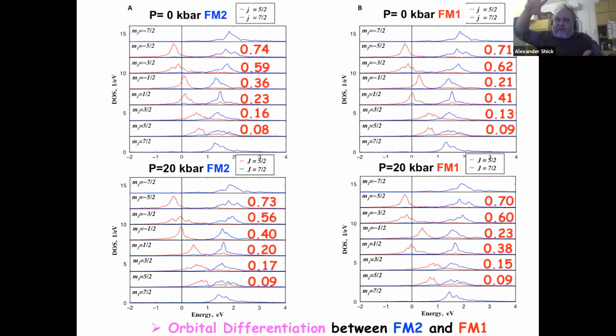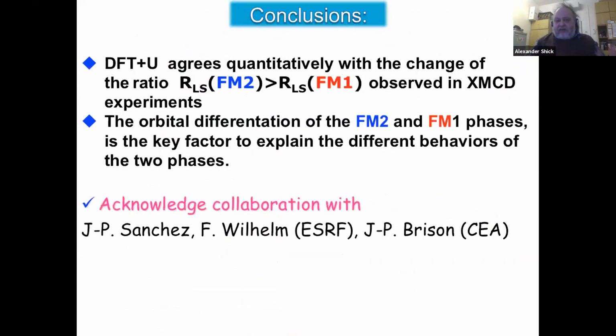So when you apply pressure to uranium germanium-2, you change not the total occupation of the F shell, but the electrons are redistributing between the different orbitals on the uranium atom. I will make some intermediate conclusions: our DFT plus U calculations agree rather well with the experimental observation showing the change in the RLS ratio when you go from the high moment to the low moment state of uranium germanium-2, and we found the reason for that as an orbital differentiation between those two phases. At this point, I want to acknowledge the collaboration with my colleagues from the ESRF.